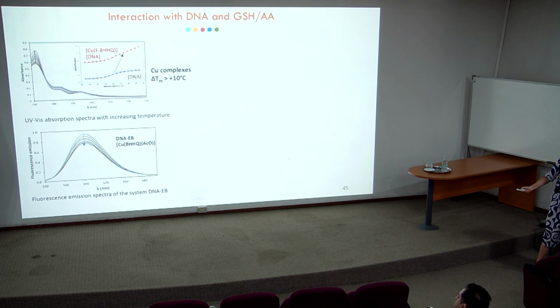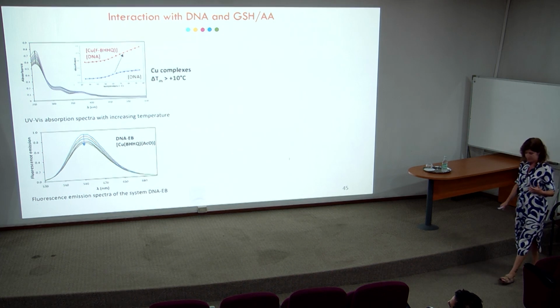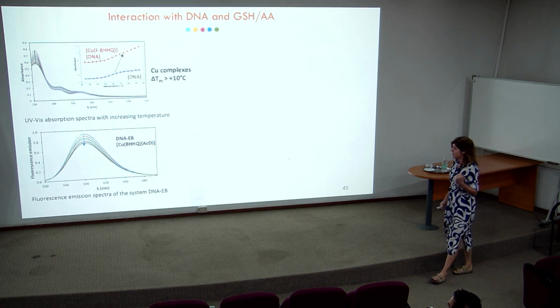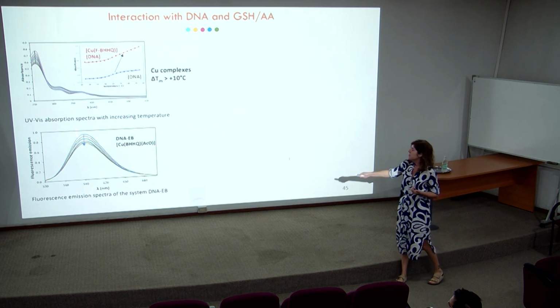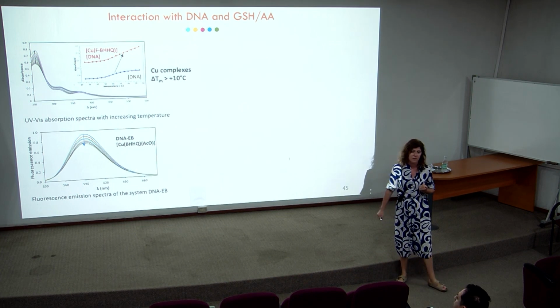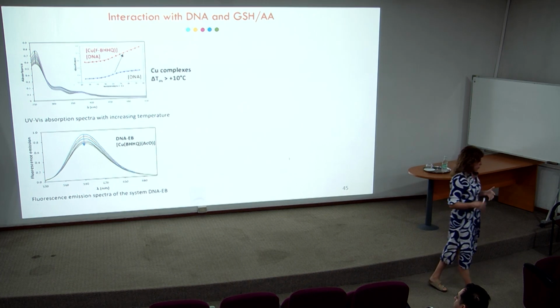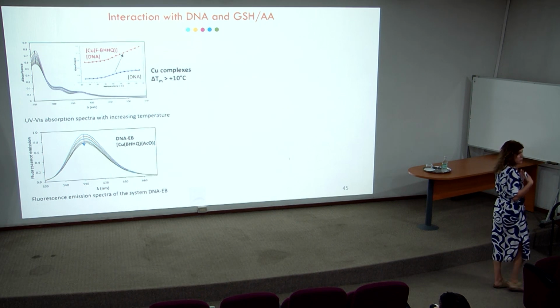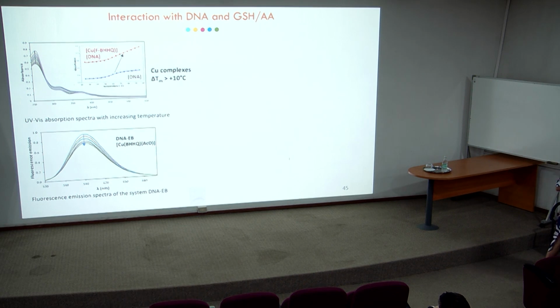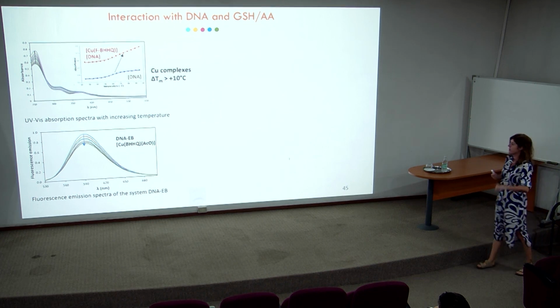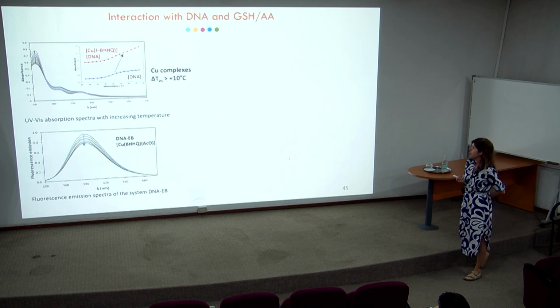Fluorescence emission spectra titrations were done in the presence of ethidium bromide, which is an intercalator. We see just a very small decrease in the fluorescence intensity, so we do not believe that these compounds are able to intercalate into DNA. They cannot replace ethidium, which is intercalated into the DNA bases.